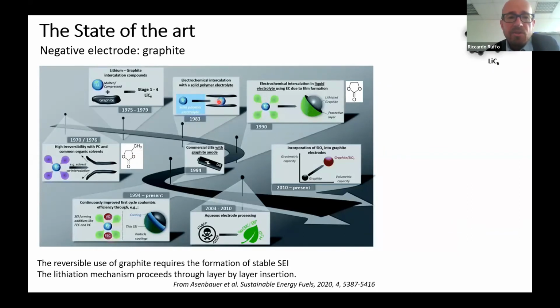Later, it has been demonstrated that lithium can be reversibly intercalated into graphite thanks to the use of a polymer. And at the end, we discovered that the reaction is perfectly reversible if you use ethylene carbonate. So if you look at the difference between ethylene carbonate and propylene carbonate, it's really tricky to understand why this molecule is working, why this one provokes the exfoliation of graphite. And the reason is again this stable SEI layer formation at the interface.